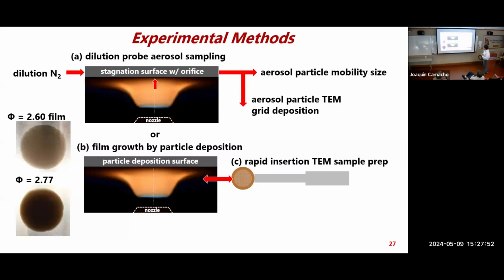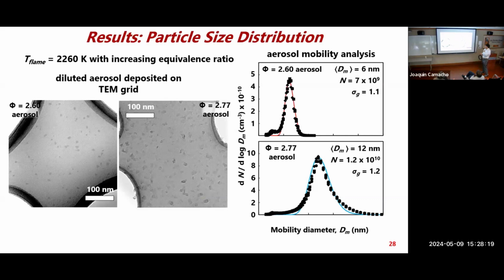So reminding us on these measurements, I looked at high resolution TEM by growing this from a diluted flow, collecting film or particles from a diluted flow, collecting these films over time from this deposition surface, and a rapid insertion of this TEM grid. We see graphite structures, graphenic nanomaterial structures, but there's a lot of variation depending on how we collect it. So here is a microscopy picture, low magnification, to try to get the particle size distribution of a high temperature flame collected from a diluted flow. And over time, these particles indeed stick to this microscope substrate, and we can get an idea of the size distribution, just count them and get a histogram.